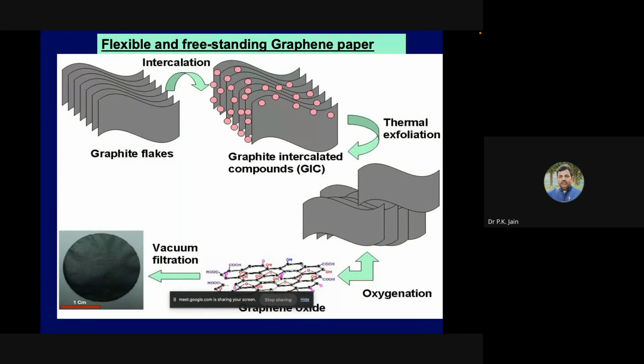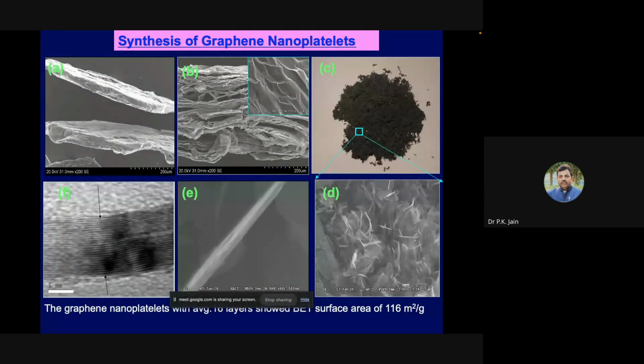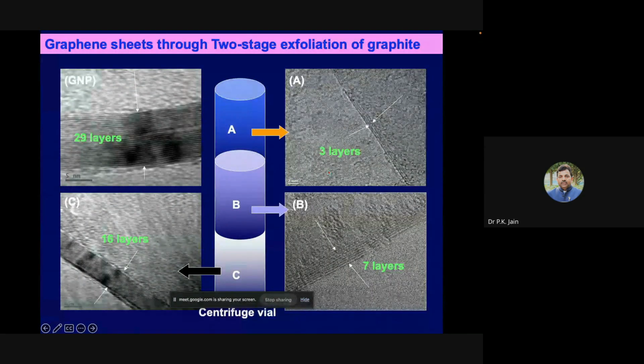Now, we have used a different technique because our strength is making exfoliated graphite. We have taken this graphite, expanded graphite, and tried to sonicate it and then convert it into graphene, and these things we got, we made into a bucky paper. Now this is few-layer graphene, and if you do the proper segregation, you can get it from more than 20 layers, more than 15 layers, more than 7 layers. Even some parts are around 3 layers.